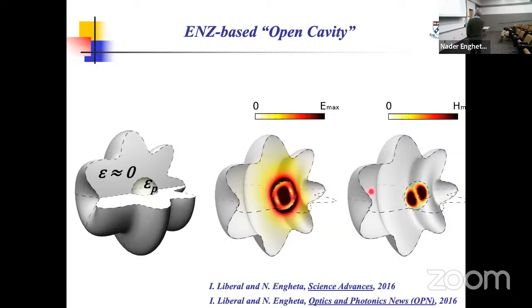Now, this is a very, very interesting mode. Because if you are sitting, by the way, at this ENZ shell, you notice that at every point in this ENZ shell, that mode has the electric field, but there is no companion magnetic field to that. That's actually quite a fascinating thing, because you can have a scenario where your electric field is oscillating with time with a frequency omega, but there is no magnetic field associated with that. And that happens, by the way, in this epsilon near zero.